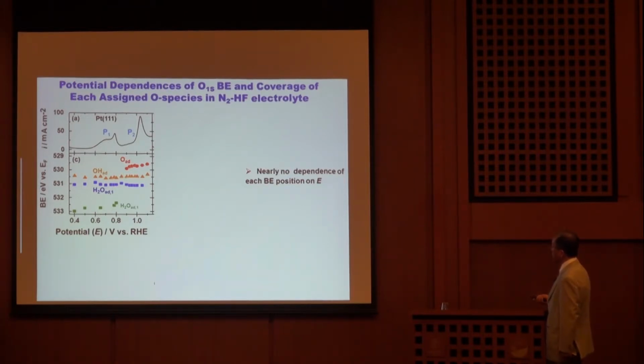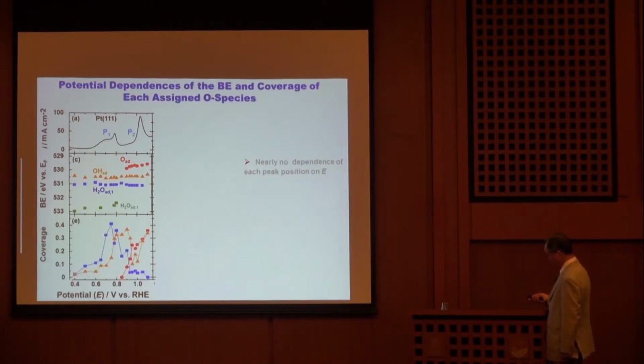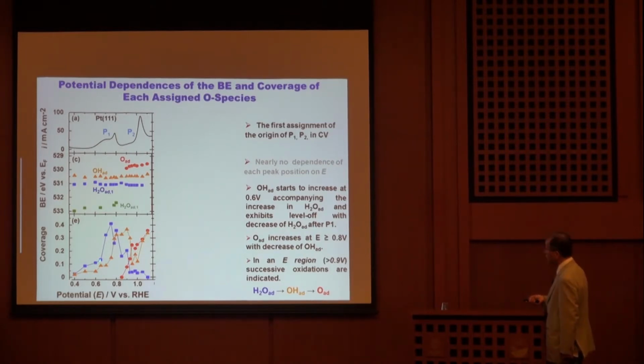As you can see, there is nearly no dependence of each binding energy position on potential. And the OH species, orange color, start to increase at 0.6 volt, accompanying the increase in water molecules, and level off with the decrease of water after this single crystal peak 1. And the O species increase at 0.8 volt or beyond with decreasing OH species. In a potential region higher than 0.9 volt, successive oxidation is indicated as shown here.